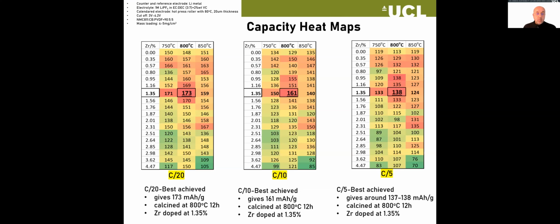I'll just explain these diagrams. This is the percentage of zirconium doping up to about 4%, and this is the heat treatment temperature that we used. It would have been for a standard number of hours, I don't remember how much, probably about 3 hours or something, because at this stage we were just looking at one heat treatment to get an idea of capacity values.